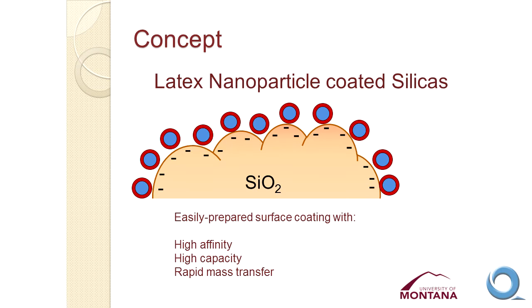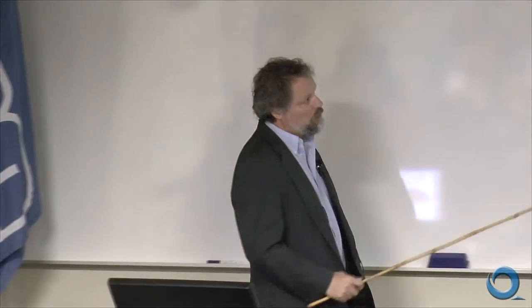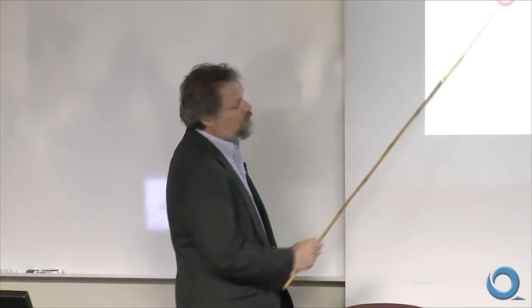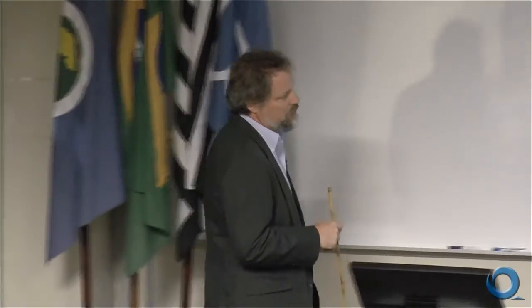And silica, at sort of intermediate pH, has a negative charge on the surface because the silanol sites will dissociate and leave anionic sites on the surface. So the idea was to prepare cationic nanoparticles and have them adsorb to the surface through ionic interactions and be immobilized on the surface. And these nanoparticles would then be the material that actually interacts with the solutes and extracts the solutes from the matrix.